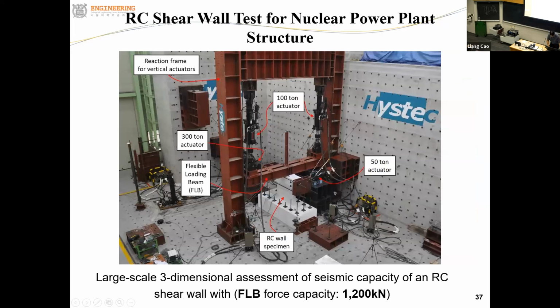Okay. We also conducted another test using the flexible loading frame. This is the test setup of the reinforced concrete shear wall of the nuclear power plant structure. That's the test specimen, RC shear wall. And it is subject to the in-plane deformation as well as the out-of-plane deformation. We also apply the axial force to this shear wall, using these two large capacity vertical actuators connected to the flexible loading frame here. This flexible loading frame was designed to have the force capacity up to 1,200 kilonewton. We actually applied 1,100 kilonewton during the test.